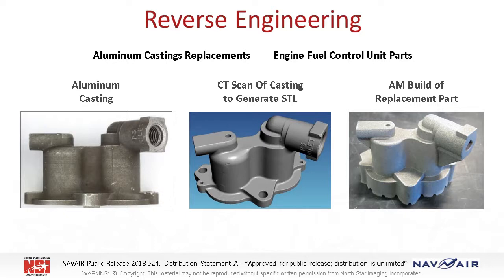Once the part is built, then we can do a CT analysis of the part, as well as create a file that we can plug back into an FEA model, and if necessary, understand where we may need to beef up the part relative to the AM build material properties compared to the casting properties. And then obviously the part goes through the normal qualification testing and material properties testing from coupons, etc.